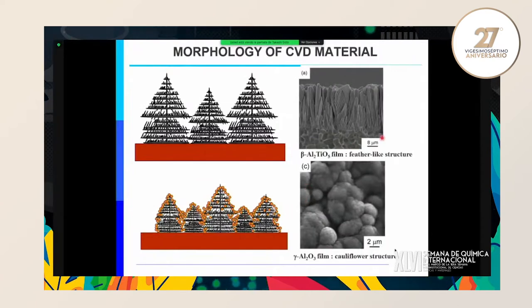And sometimes nanoparticle formation causes a dendritic microstructure, like this one, or it is called a feather-like structure, like a feather of birds. Since this film is porous, this is sometimes useful, for example, for thermal barrier coating, but usually it is not a good morphology. So nanoparticles may deposit on the dendrite, and this is called a cauliflower microstructure. This is a common microstructure of CVD. It may contain impurities, and it is porous. Sometimes it is useful for catalysis, but usually it is not so good a microstructure.